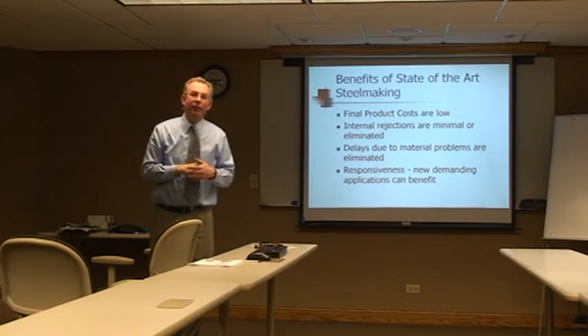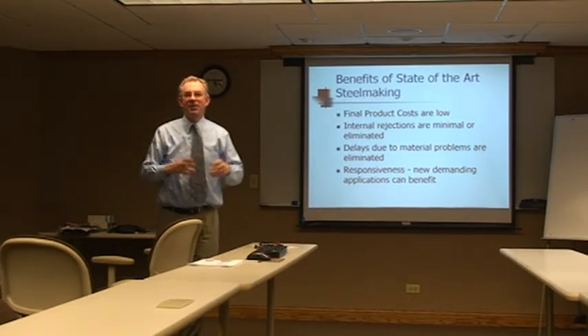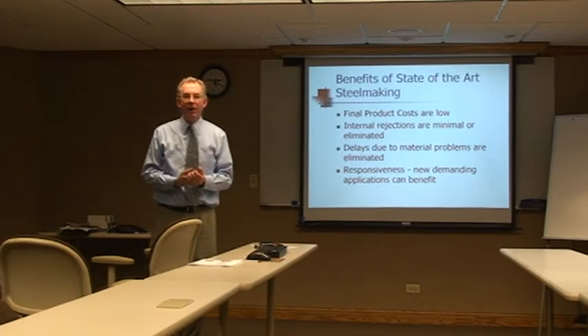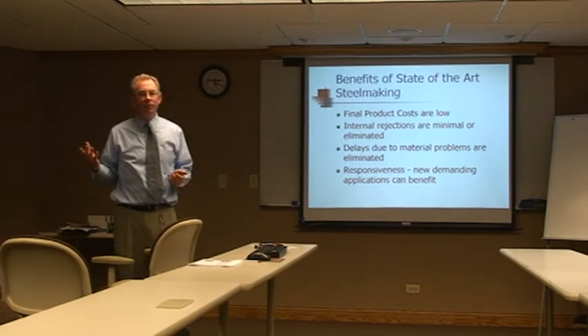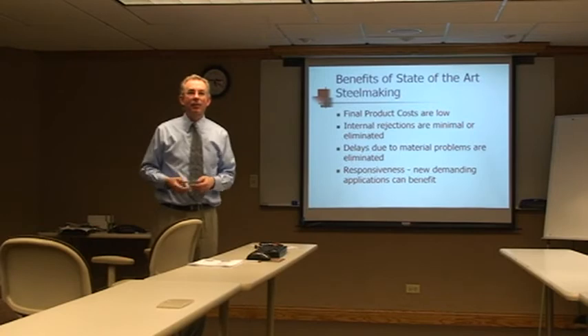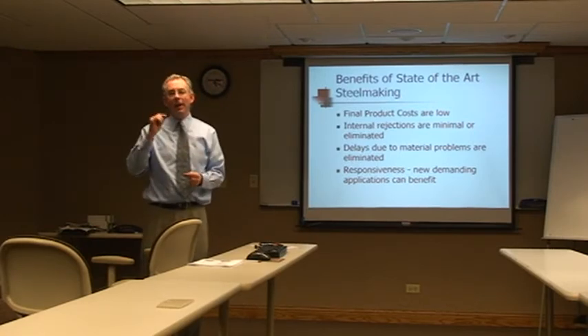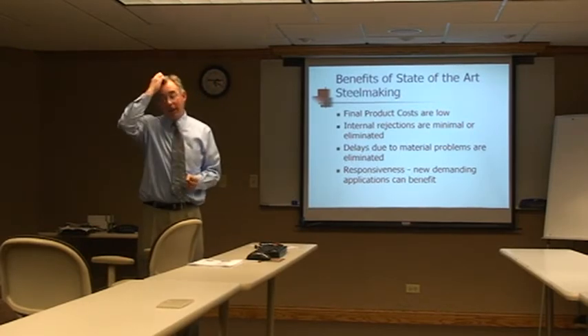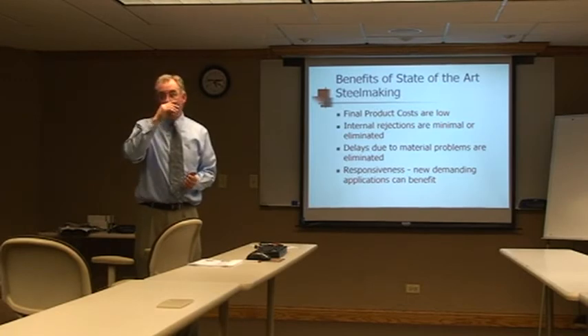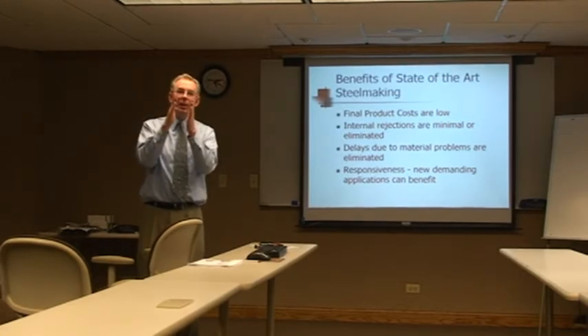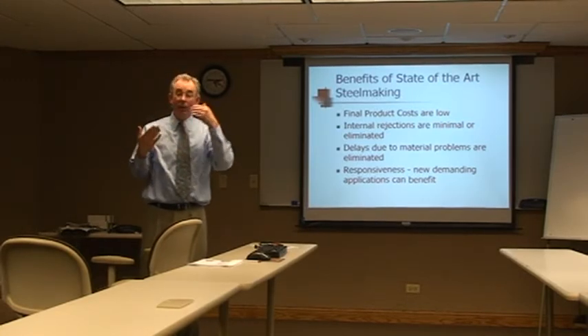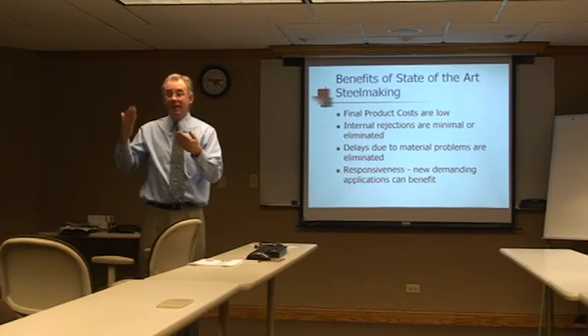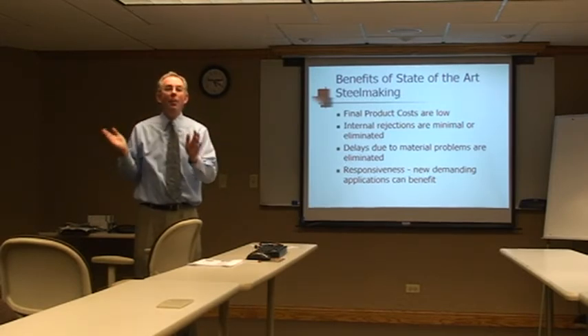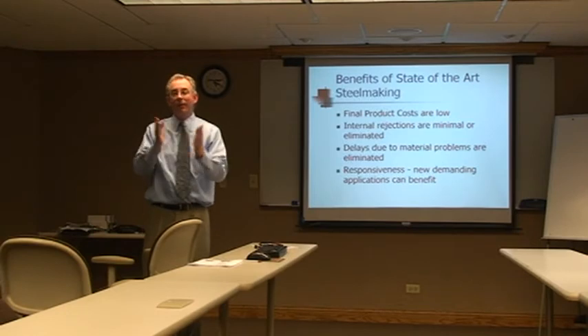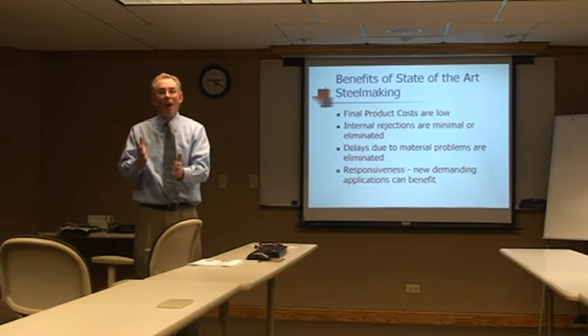So if we supply 75 heats of 4340 to Scot Forge in one ingot size or various ingot sizes, the variation in the teeming temperature will be less than 0.5%. The chemistry will be extremely tight and consistent, so that when you're looking at heat chemistries from one to the other, they're practically identical. There's some variation, obviously, but they're practically identical.